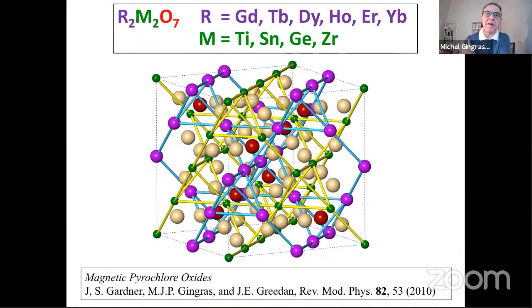So the oxide pyrochlore structures are a very rich family of compounds. And this is the general formula here, R2M2O7. There are a number of metallic such systems, but the large majority are insulators. You have two types of cations. You have lanthanide ions, the 4f series, such as gadolinium, terbium, and so on. These are trivalent cations. And you have transition metal ions like titanium, tin, germanium, and zirconium for the M site. And then you have the oxygens.